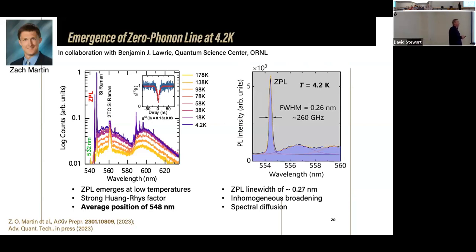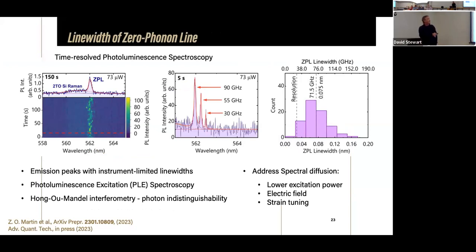In our case, it's still relatively broad. It's 260 gigahertz, even at 4.2 K. But that's, as we figured out, because of spectral diffusion. So we clearly see that there is quite significant spectral diffusion. You see the position of the central line just as a function of time diffuses. And as a result, we have this broadening.